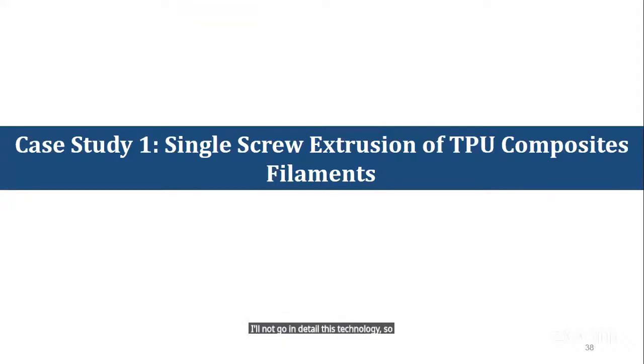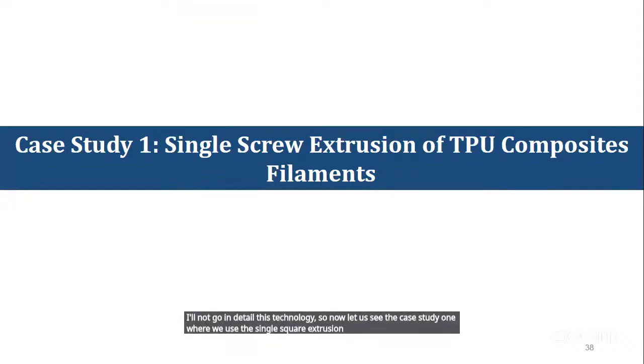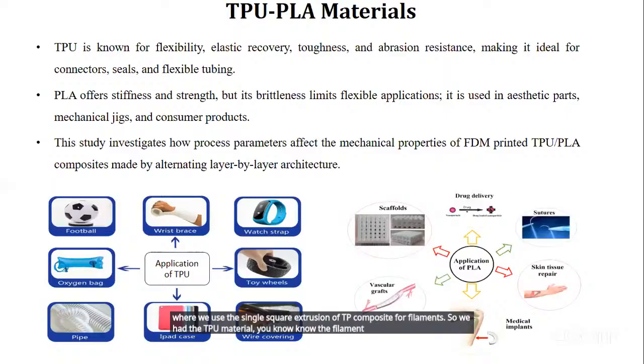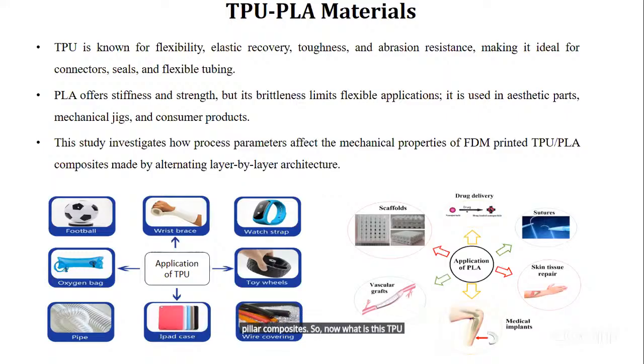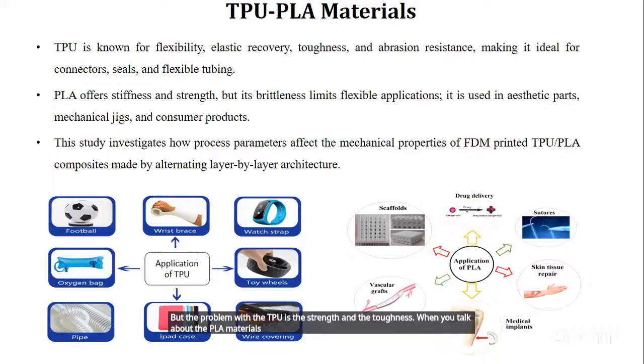Now let us see case study one, where we use single screw extrusion of TPU composite for filaments. We had the TPU material as pellets, and we also purchased PLA, and we tried to mix some compositions to produce TPU PLA composites. So what is this TPU? TPU is known for high flexibility, elastic recovery, toughness, and abrasion resistance, ideal for various applications like football, wrist braces, biomedical applications. But the problem with TPU is its strength and toughness. PLA has higher toughness and strength compared to TPU, but it is brittle, right? But it is also used for various purposes.